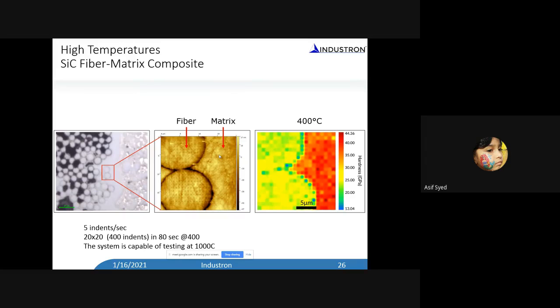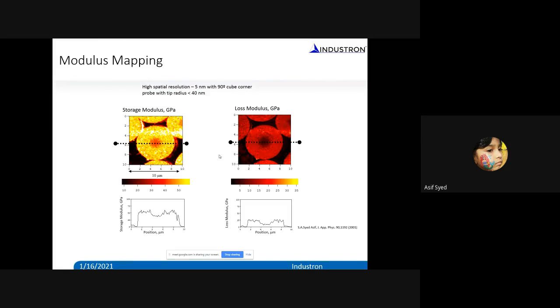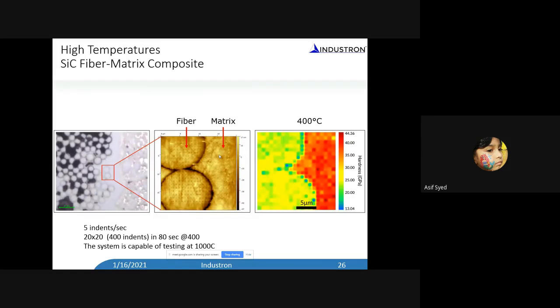Okay. So we also have another technique where we can go and do an indent. In the previous case, you just measure the modulus, but you don't measure the hardness because the depth, we are still within the elastic contact. But if you want to measure the hardness, which is basically a plastic deformation, you do an indent, and you can do those indents very fast.